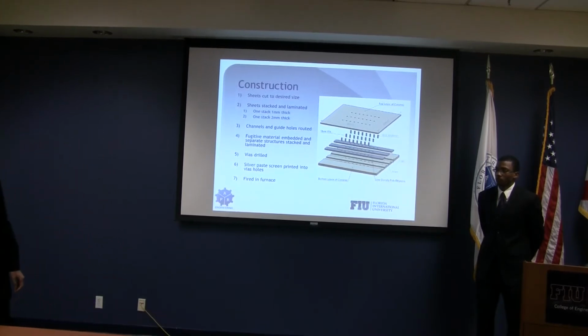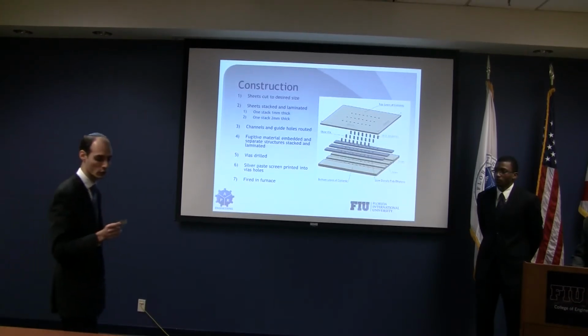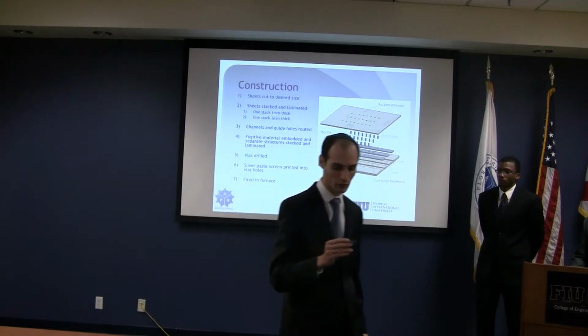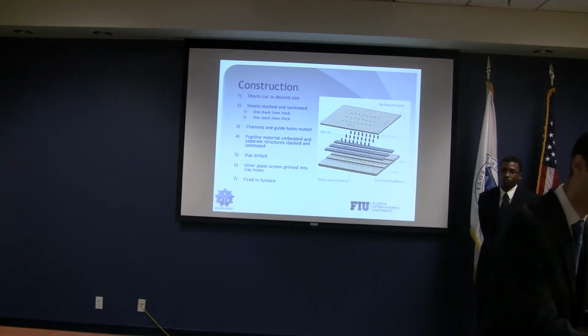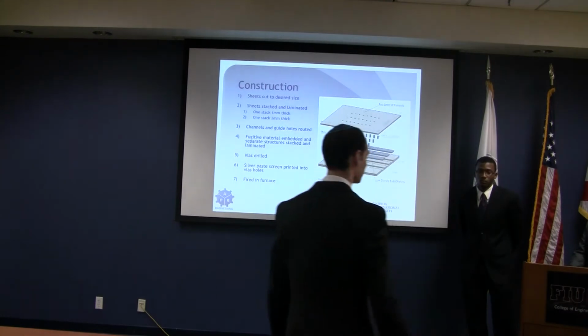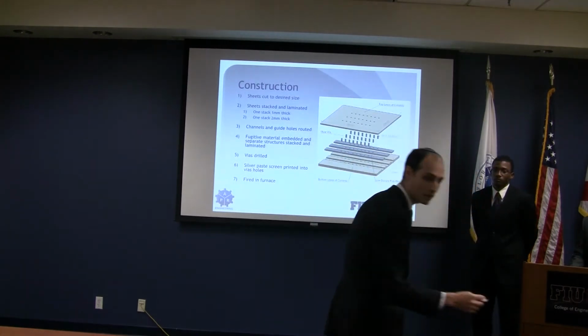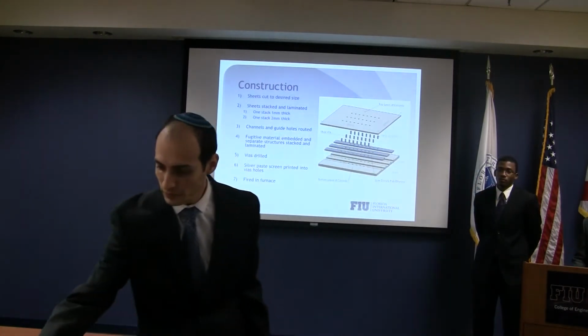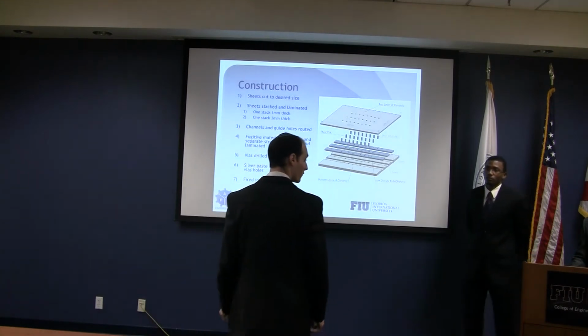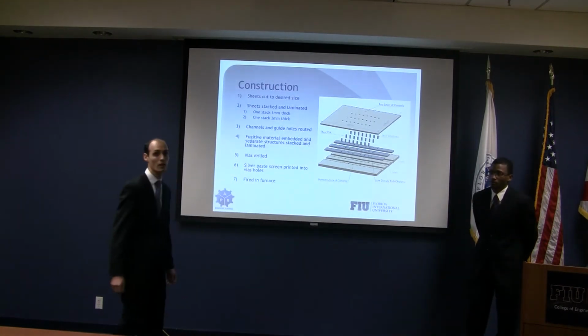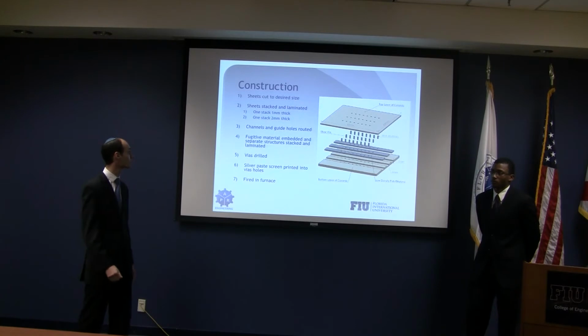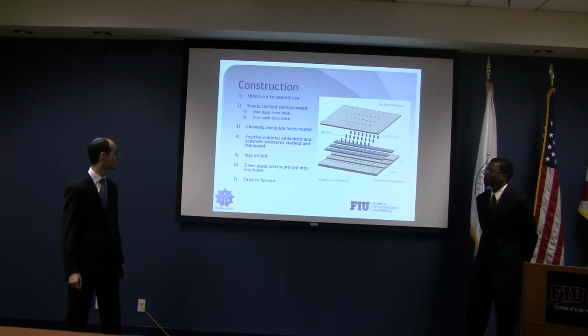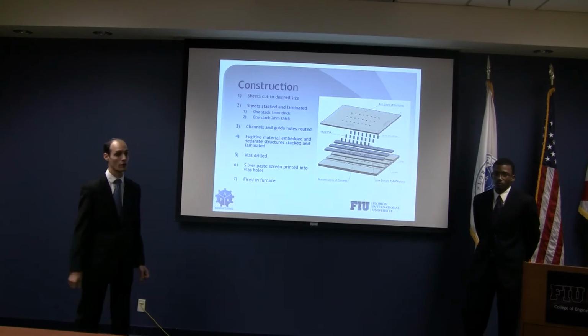During the silver filling process, we had to optimize which silver we wanted. So we have 3 different silvers here, trying to figure out actually which one would work best. And we have it over here done in regolith to see which one would work best. It ended up being that it was the same silver that worked the best out of all of our choices. And so we went ahead with that one. And then we fired them as the firing profile that we had done earlier.